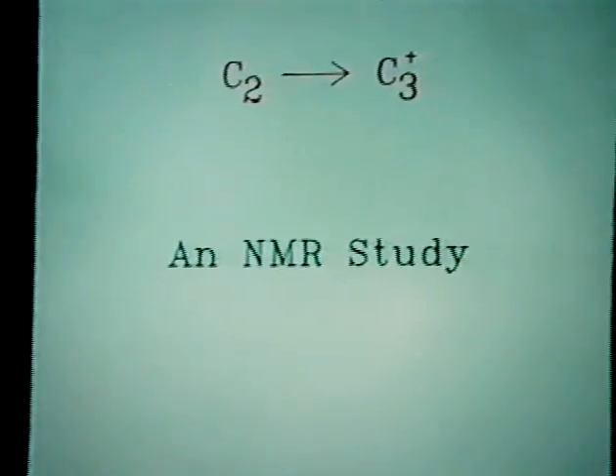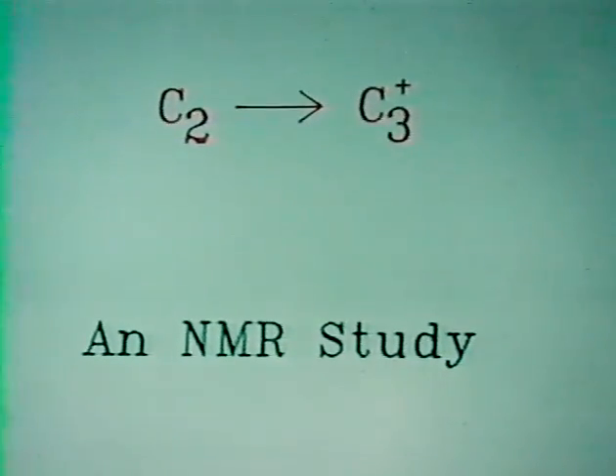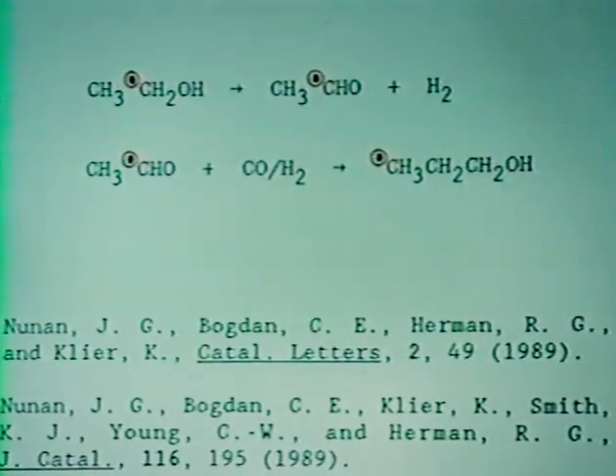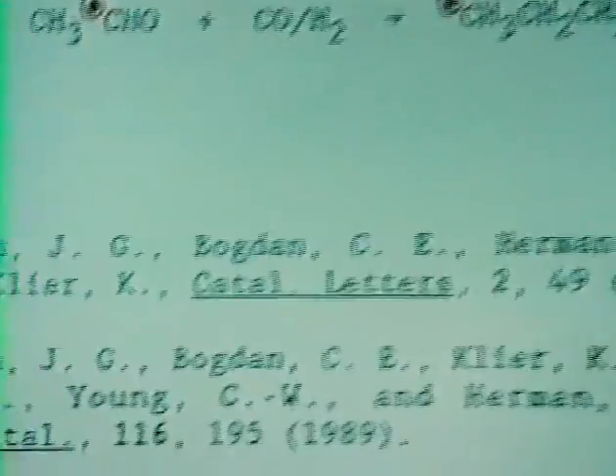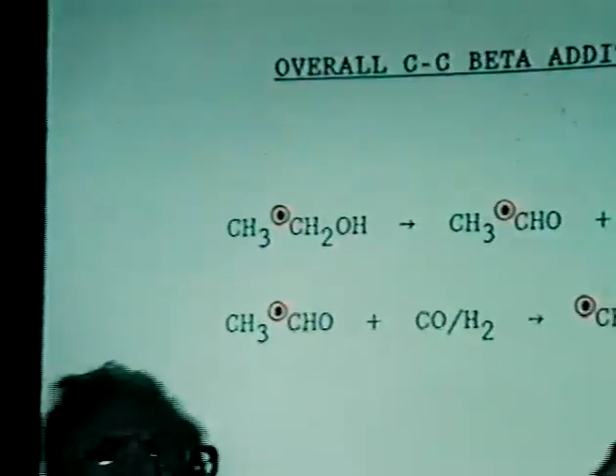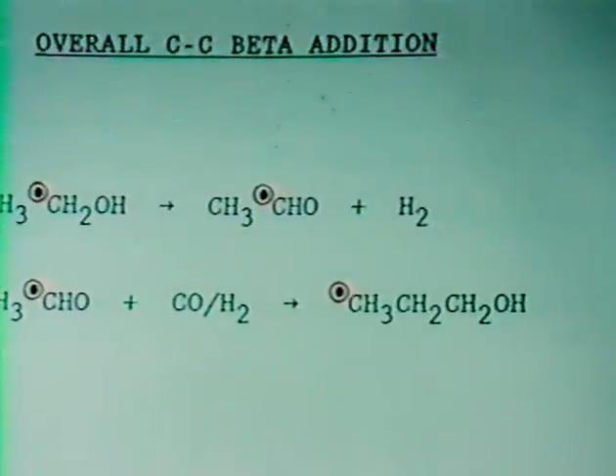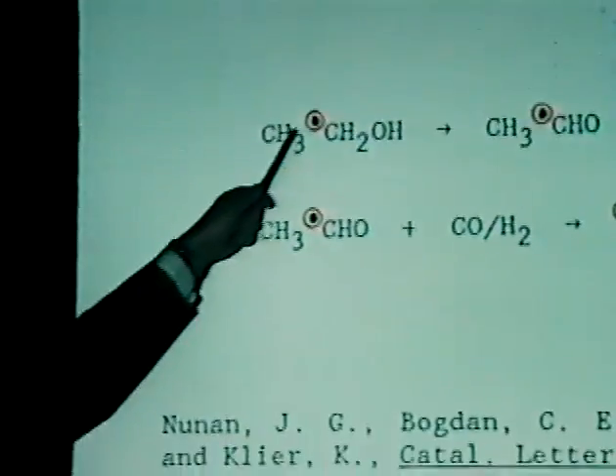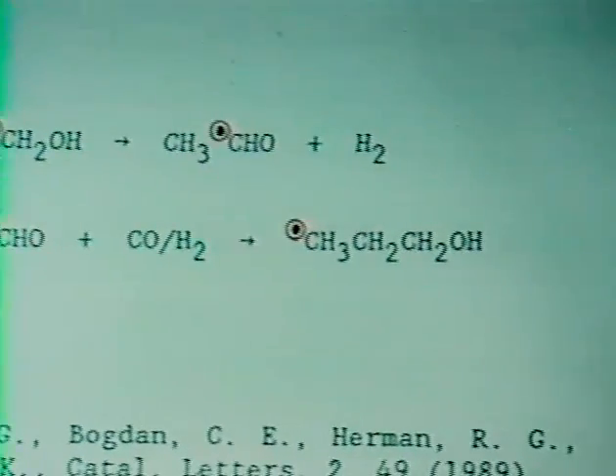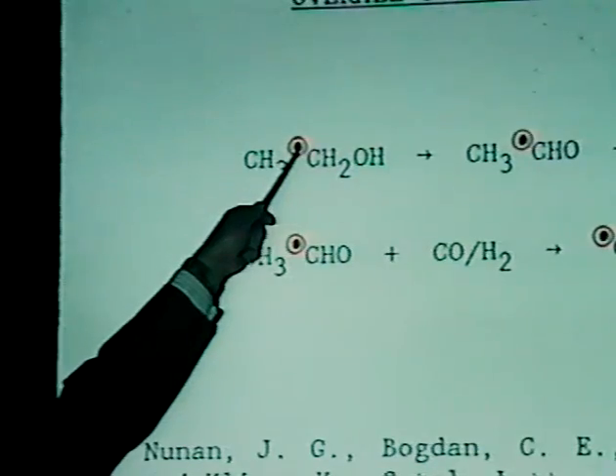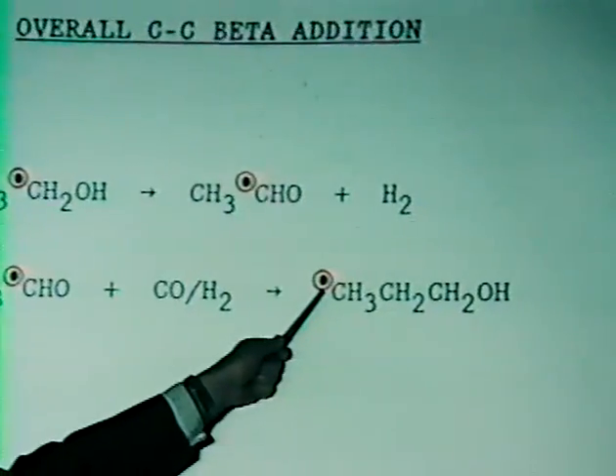You can do NMR, of course, and you can do C13 NMR. You can identify in the product every carbon without separation of the mixture. The result now over the copper zinc oxide alkali doped catalyst is as follows. Now we inject the C2 alcohol because we are making the C3 alcohol by addition of the synthesis gas. The C2 alcohol labeled here with the carbon 13 gives us over the cesium doped copper zinc oxide exclusively the label here.